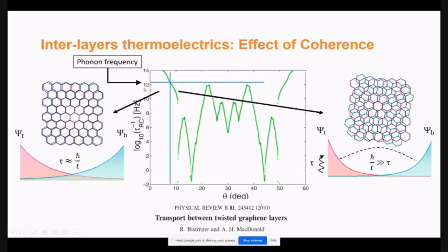It turns out that when the two layers are closely aligned below 5 degrees, then electron tunneling is essentially dominating, and phonon frequency is a slow process in comparison, and it is not really affecting the thermoelectric power at all. It is obeying the Mott relation because we are in the diffusion, or the Landauer-Büttiker regime, in which you calculate the transfer from one layer to the other.